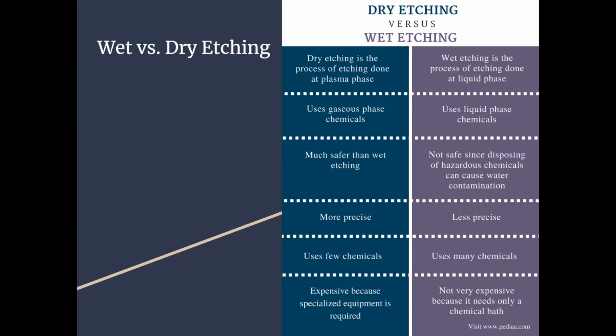As I mentioned before, dry etching is much more precise. You can get nanometer accuracy with dry etching. With wet etching, you're usually looking at a micron scale. With dry etching, you most likely have to use a few chemicals, while with wet etching you use more. The main drawback with dry etching as compared to wet etching is that it's expensive because, as I mentioned, you do have to use specialized equipment.